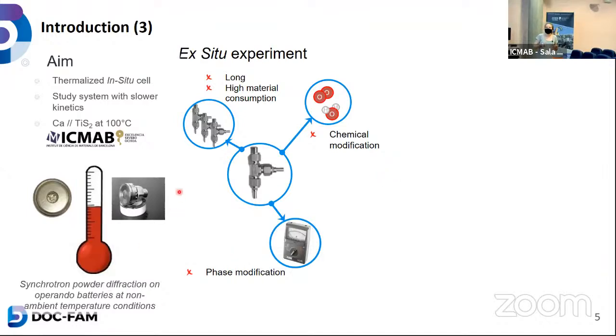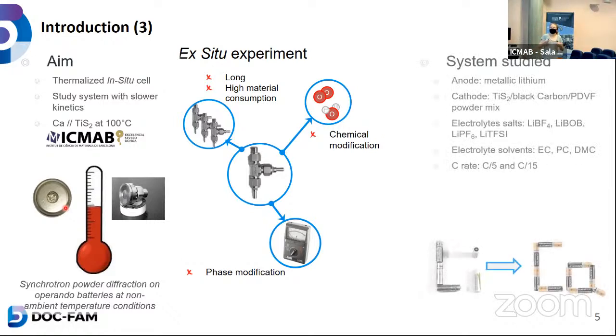We use this type of cell, which is quite similar to the one we use for ex situ, but you can do X-ray diffraction on it. And the coin cell, which you may know, is a type of cell that is used commercially. However, calcium is a bit stubborn. Calcium ion is very slow, so it's easier to do a preliminary observation with lithium and then to report all we have observed on calcium and see if there are some differences. So in the first study, I used 4 different electrolyte salts and 3 very typical electrolyte solvents.